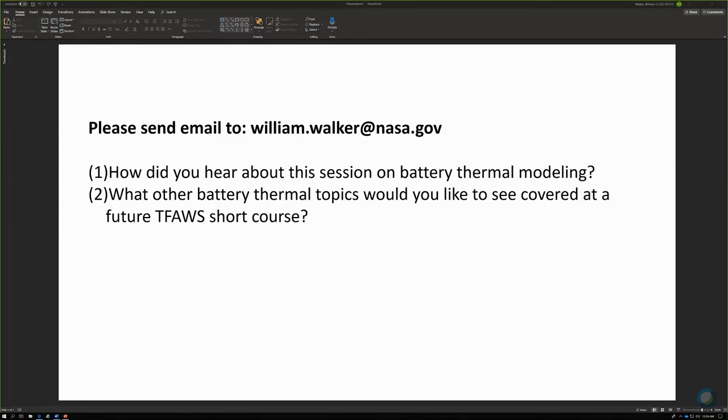You might also want to consider using an electrochemical approximation for total heat release, potentially as a function of the electrochemical energy stored in the cell. While I don't think this is the best approach, I prefer to go to calorimetric means if possible. If you don't have calorimetric means available to you, then the next best step would be to approximate that total energy release as a function of the stored electrochemical energy in the cell.